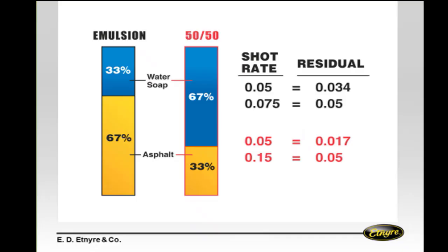I did find out that you do dilute some things. One of the shot rate problems we have is I don't know what your percentage of emulsion is, whether it's a 70-30, a 67-33, or 80-20, or whatever. But if you're adding cold water to an already milled product that's come from the mill already blended, you run the risk of shocking the oil to the point that the emulsifiers actually start breaking down.